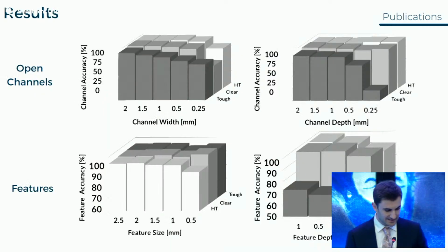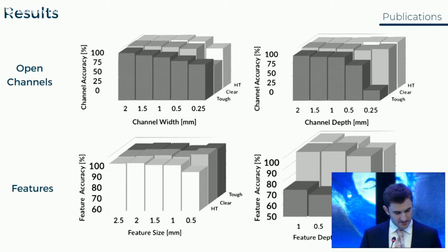So if we look at the results that we obtained, in this graph we can see the results for the open channels and the superficial features, and we can see that there is not a great deal of difference between the three resins selected. Maybe the tough resin slightly underperformed in comparison to the other two, but overall we can see that we achieved a good accuracy with dimensions at around 250 and 500 micrometers.